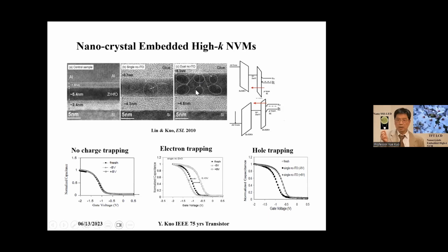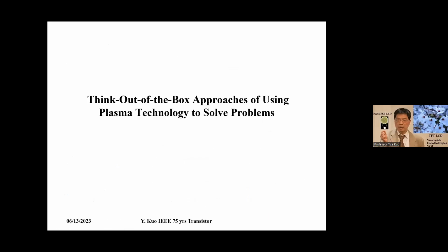And for the embedded metal, there are many kinds of layers we can deposit, with materials from different nanocrystals. This shows that if there is no nanocrystal, the high K has no hysteresis, no charging. But if we embed a different material, we can make it prefer to trap electrons or prefer to trap holes. So in other words, we can embed nanodot materials to separately store electrons and holes. And those are all done by the sputtering method. So those are in the manufacturing process, using manufacturing equipment.